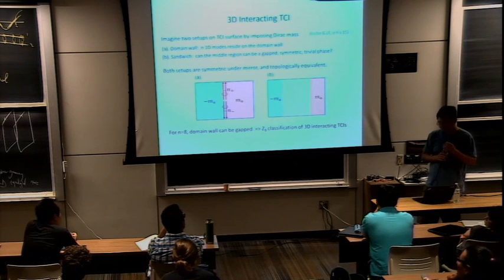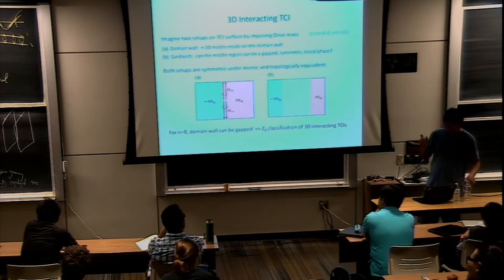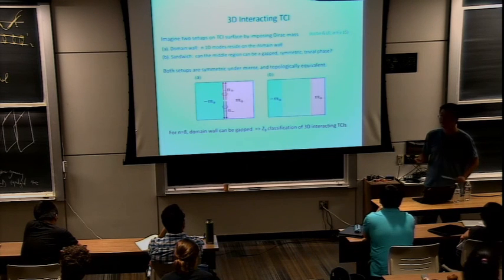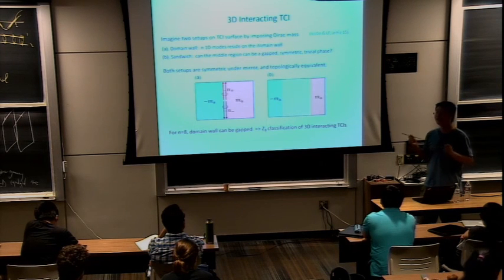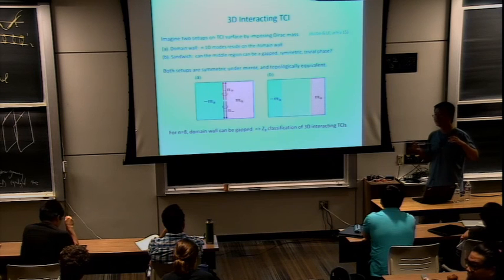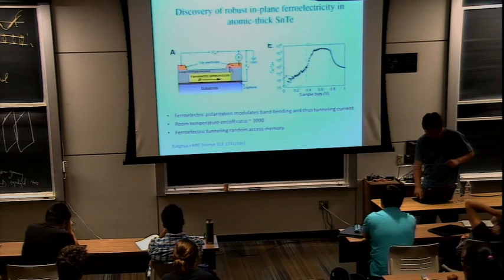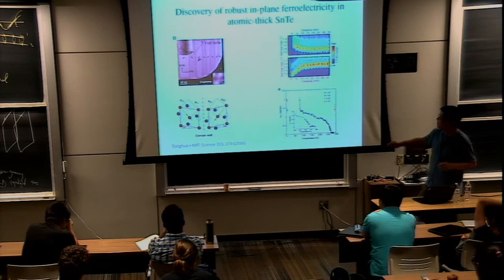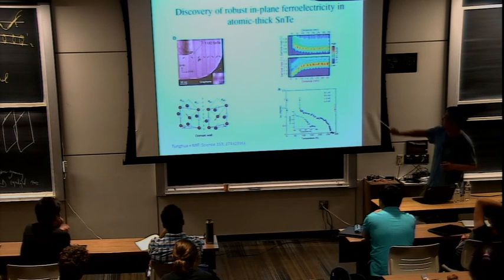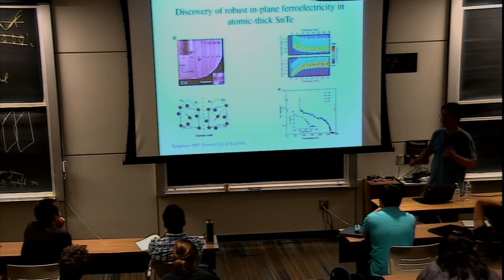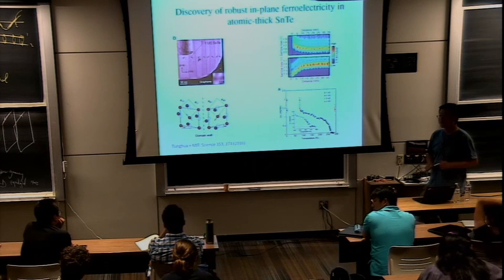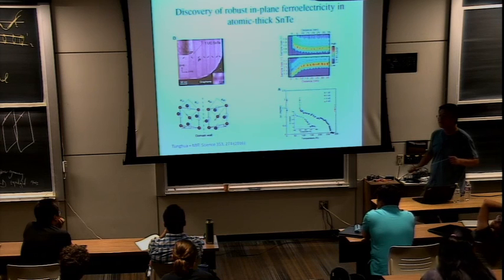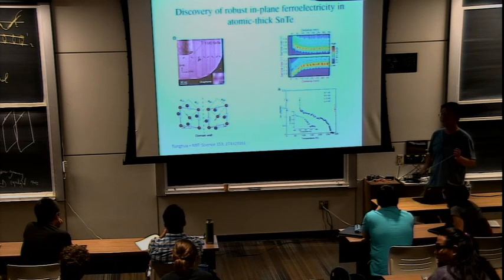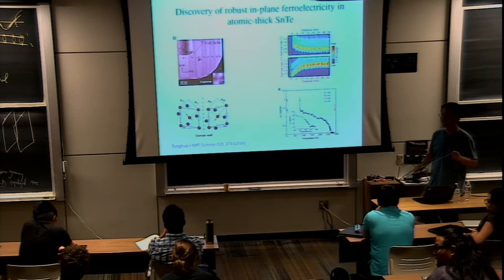Yeah, that is the case both from the bulk distortion of that material. It's also the case from the recent experiment on lead-tin selenide, where distortion only occurs on the surface. And even for this experiment, ultra-thin few layers of the material, the distortion is also along this particular high symmetry axis. It just seems to be the case. In principle, it could point in other directions. No, then the surface will be fully gapped, right?